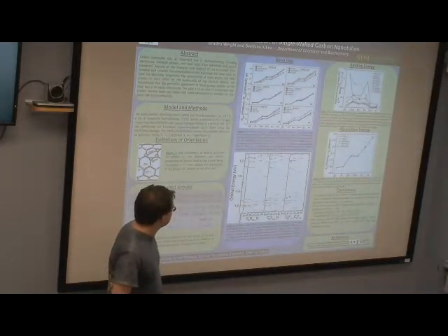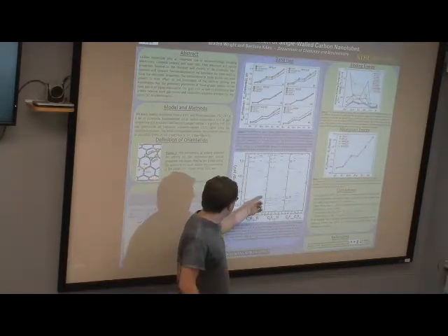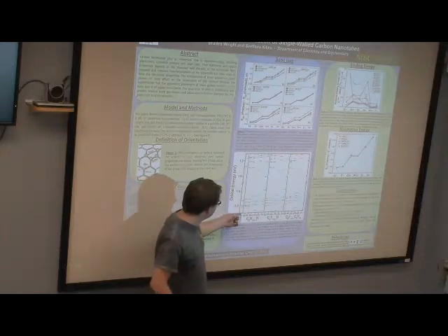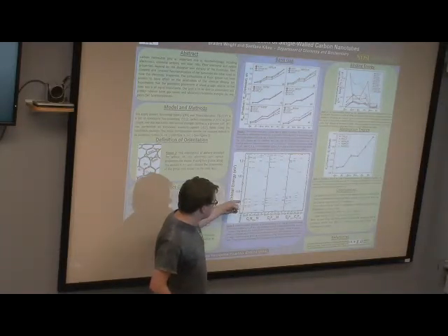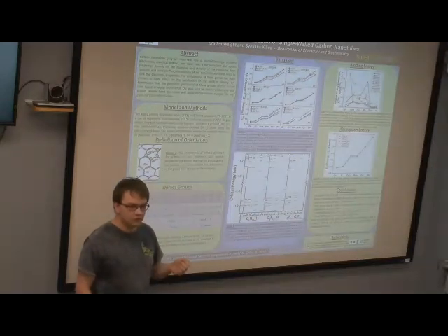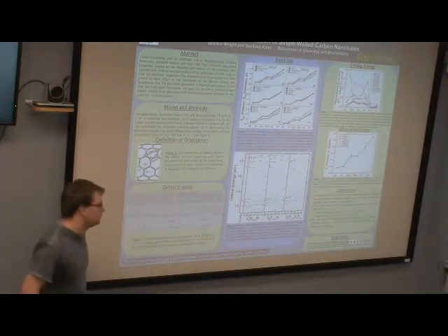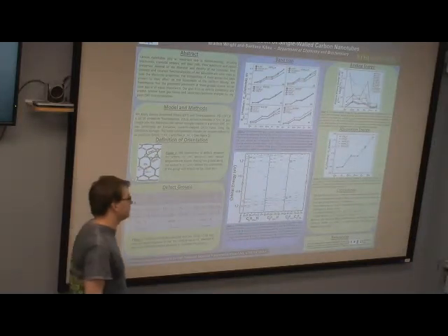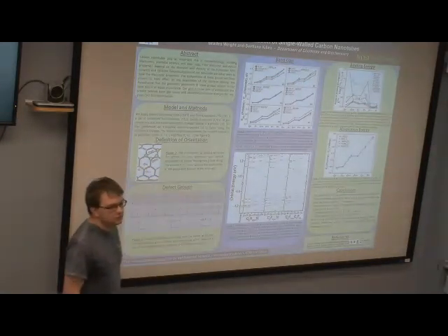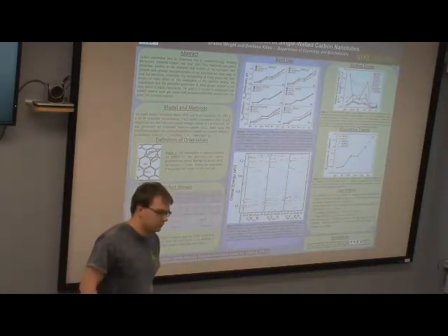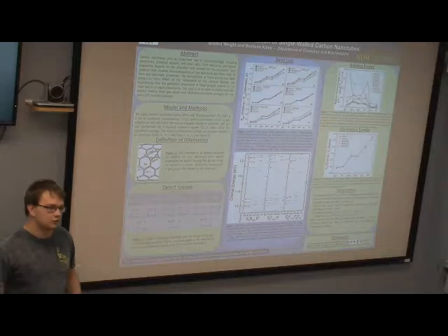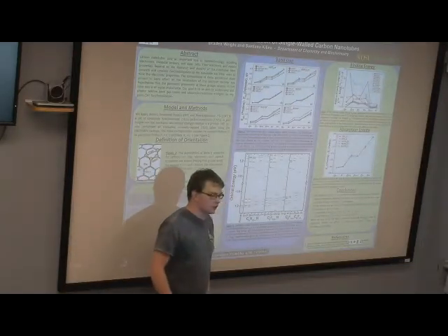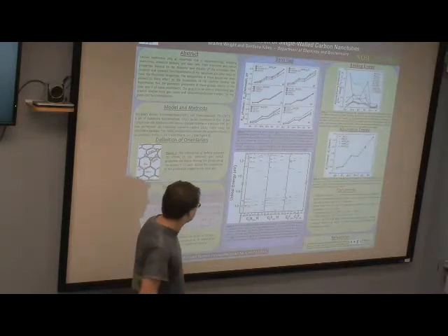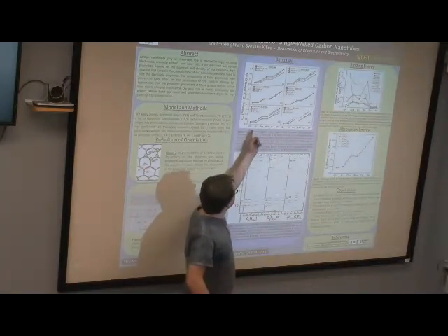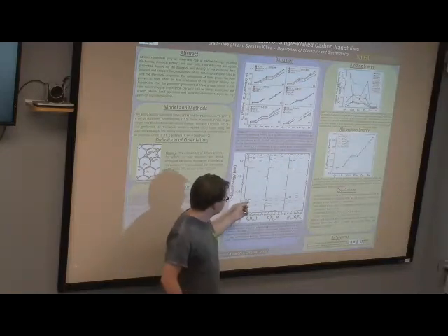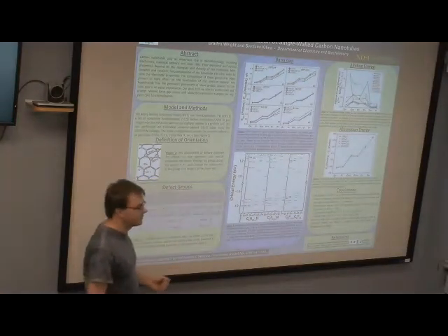And to illustrate that, it's kind of hard to see here, but if we look at the pristine tube, obviously all of the HOMO-LUMOs of the defected tubes will be pushed up into the band gap. You can attribute that partially to the loss of symmetry in the carbon nanotube, and also to an inductive localization of the wave function, or the electron density, near the defect or on the defect in some cases. And as I continue ordering them in the same fashion, they get smaller and smaller, so the HOMO and LUMO get closer and closer together.